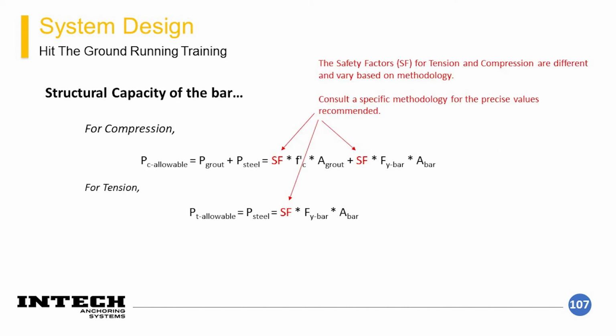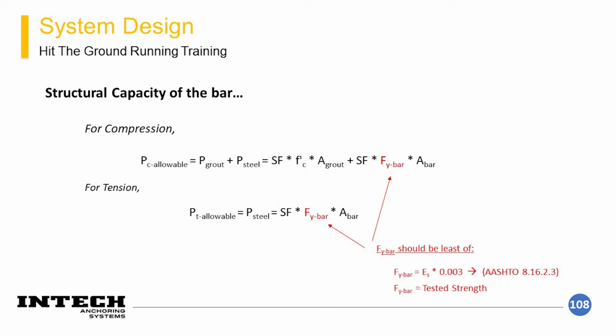So these equations are relatively simple, but have a few nuances. The safety factors are different from one another, and there are different factors of safety based on the methodology you are choosing to use for design, so make sure you are paying attention to that. Another key principle is related to strain compatibility. So we could use a really high yield strength bar, however the grout would likely fail at the strain required to fully engage the steel yield strength. Typically we limit this yield strength of the bar to 0.003 times the elastic modulus of the steel.